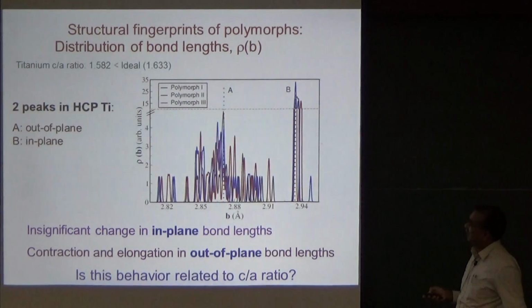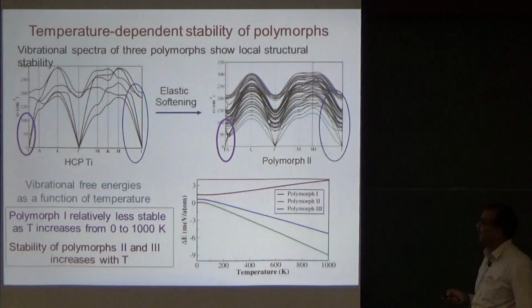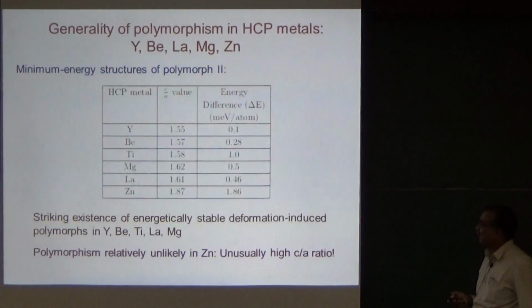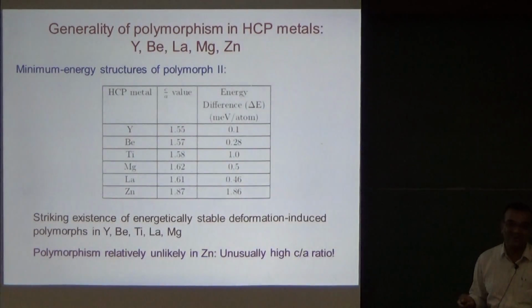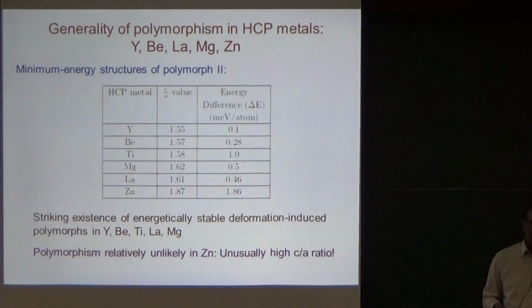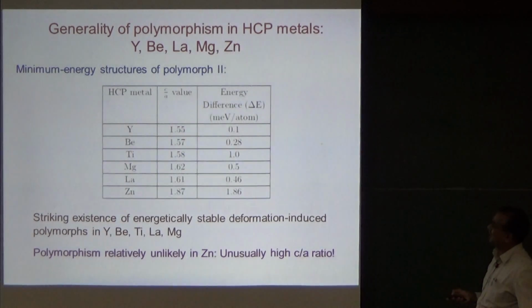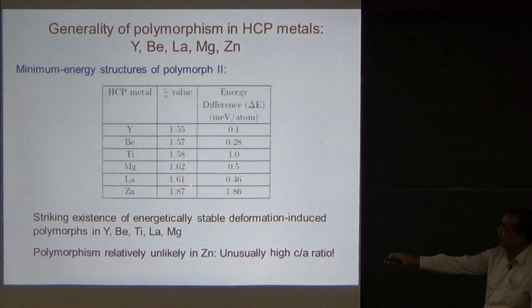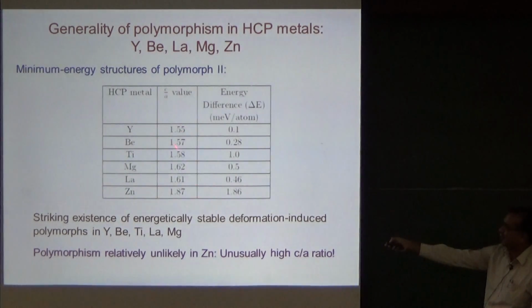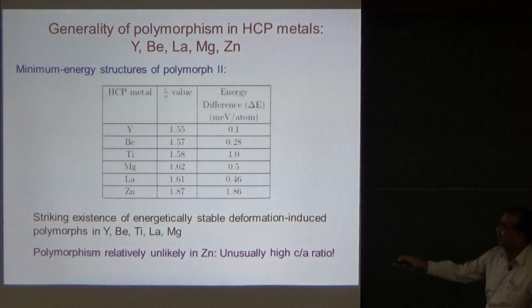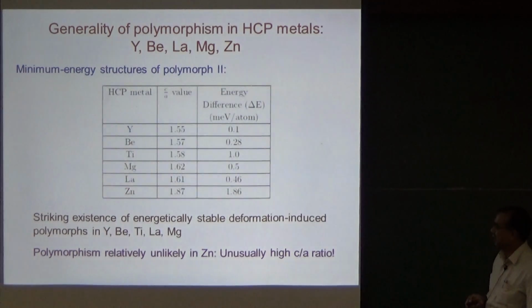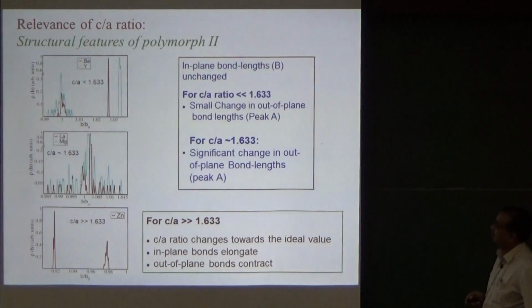Then we did lots of analysis to find out. In fact, the difficult part was to prove that it's a different structural form because it's so similar in terms of coordination number and all. So this is what we find for other HCP metals. And you see the C by A ratio of zinc is very off with respect to the others. And this is the only exception to the rule that we found, that polymorphic mechanism.